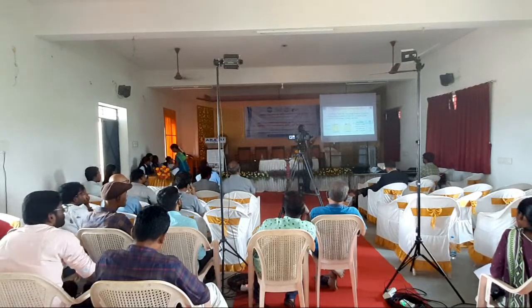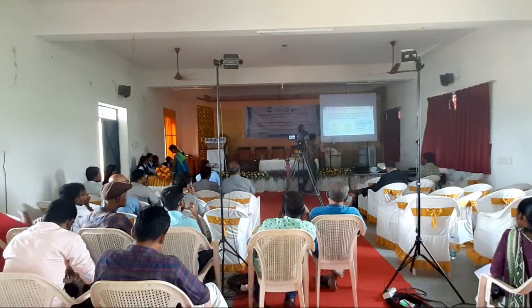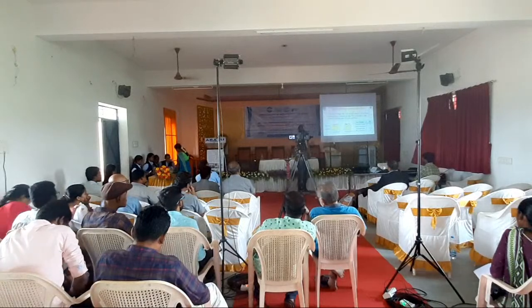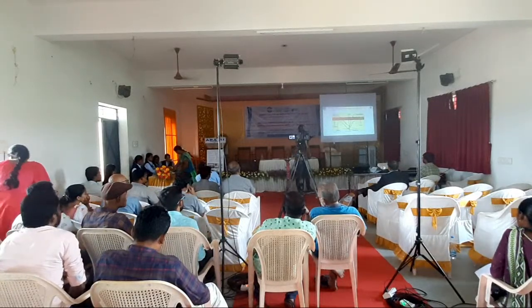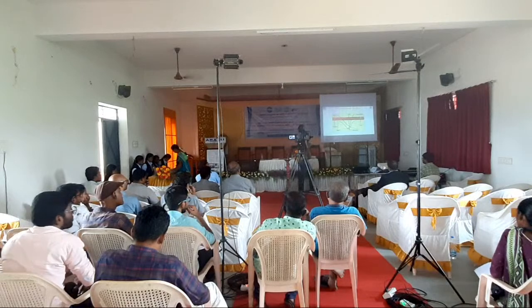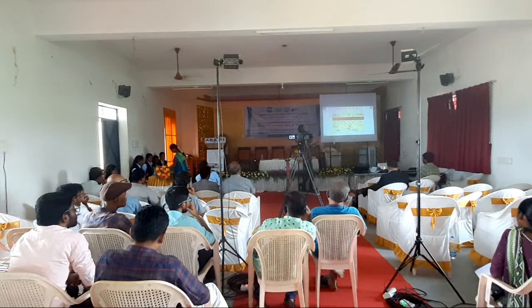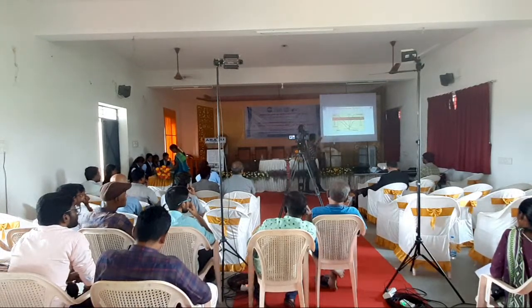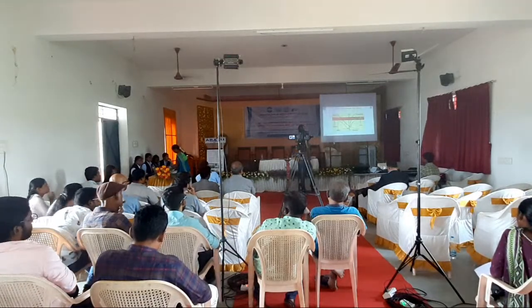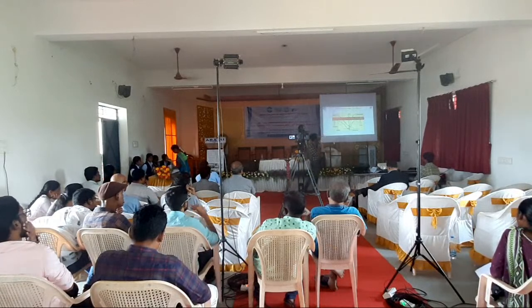You can see when you have very low PVC, there is a large distance between the particles. A high PVC means they are much closer packed. In some coatings, you need close packed pigments. In some other coatings, you don't need it. And this clearly explains, here you can see there are fewer pigments. The gloss is very high. And when the amount of pigment goes in this direction, this point is known as the CPVC, critical pigment volume concentration. If you increase more than that, you can see voids will come. Because with more pigment, the binder, the resin cannot hold it together. So voids will come. In that case blistering, and early failure of the coating can happen.